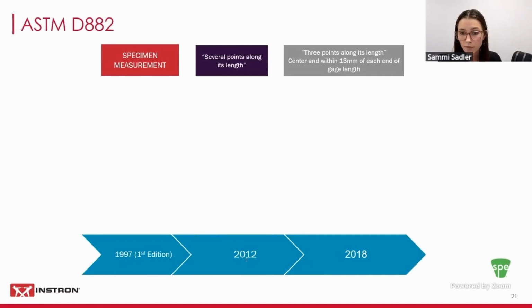The way to measure the films has been updated from measuring, quote, several points along its length, unquote, to now ensuring that you take 3 measurements, one in the middle of the material, and then 2 at either end of the specimen, within 13 millimeters of each end.